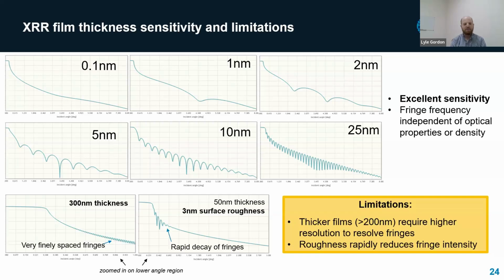One of the biggest ones is for thicker films, even just above 300 or 400 nanometers, the fringes become really finely spaced. And I've even zoomed in, so this angular range is much shorter here in the bottom left. And it becomes harder to resolve the fringes, and you need either a higher resolution measurement, or in some cases, if the film is non-uniform, you simply won't see the fringes at all, and you're no longer able to measure the thickness. Another case where there are some limitations in XRR is rough films.